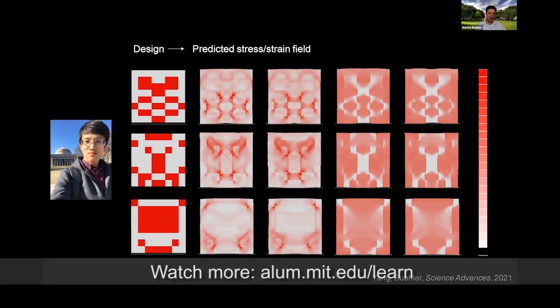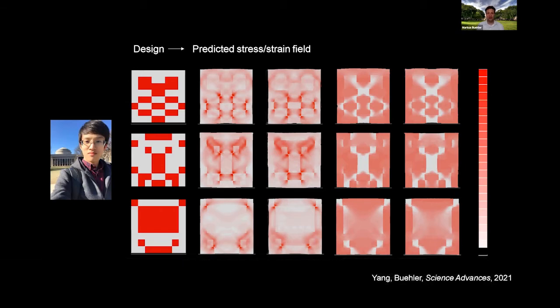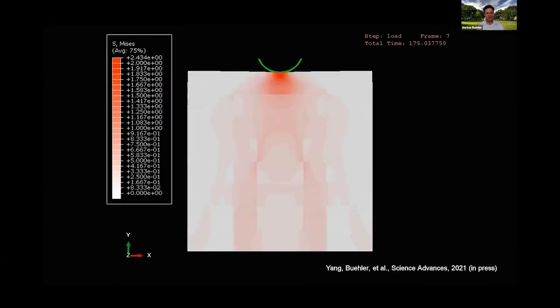So Zhenze has developed this really interesting technique where we can predict, for composites, for distributions of soft and stiff materials, multiple materials, the distribution of stress and strain fields in the system. And this essentially replaces what's conventionally done using finite element simulations. We can do indentation problems and predict complex residual stresses and predict, again, fracturing, right? So you can see here, you can simulate the propagation of cracks.